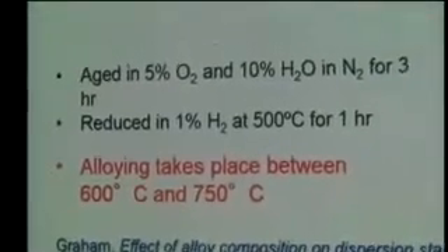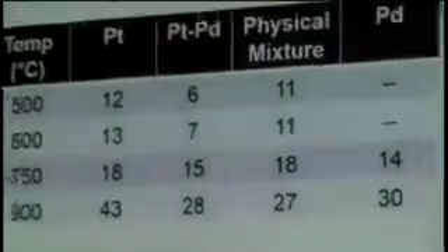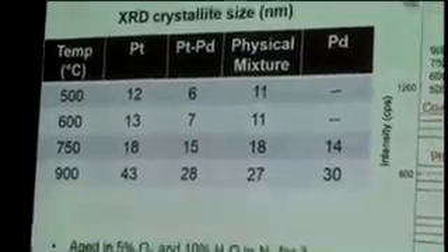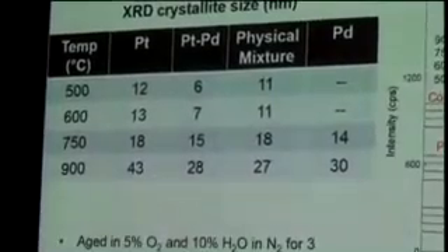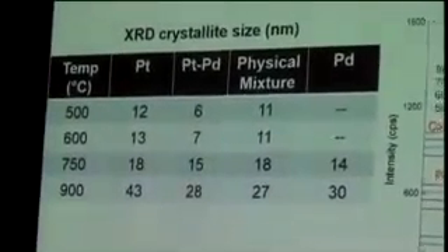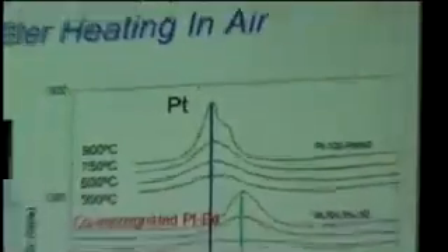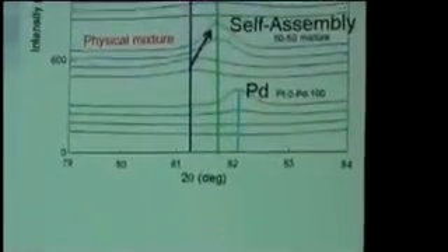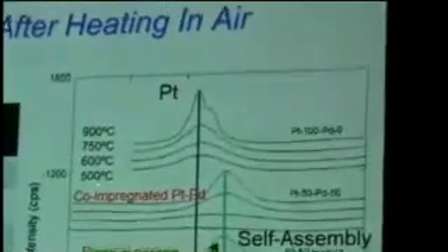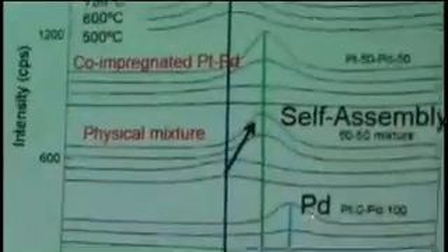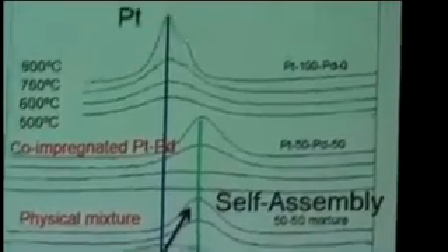So I just wanted to illustrate to you this phenomenon of self-assembly. These are the particle sizes, and I don't need to convince you that by 900 degrees, there is a difference between the platinum and palladium. And I'll show that to you. But the lower band shows it's not as significant. What's more interesting is what happens to the catalyst when it is heated to higher temperatures. So you start usually at 500 degrees, and everything is well dispersed, and you just see broad peaks. This is pure platinum. This is pure palladium. As you heat them, the palladium grows slightly, but not a whole lot. And it doesn't seem like too much.